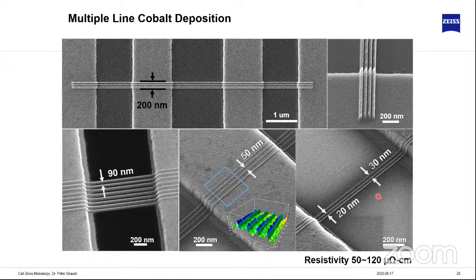We can also add a gas injection system to these type of instruments, and that enables us to do ion beam deposition like in a standard gallium FIB system. The only difference is we do much smaller size scale here. So we can generate wires that have a distance of 50 nanometers or 20 nanometers. If we do electrical tests and AFM measurements, we can clearly see they're completely separated. We can create reasonable resistivity here. And the good thing is we do not implant any gallium into these wires. As we use noble gases like helium or neon, we have a more pure deposition, and that's especially interesting if we want to deposit insulators, then we do not have any metal ions inside these insulators.